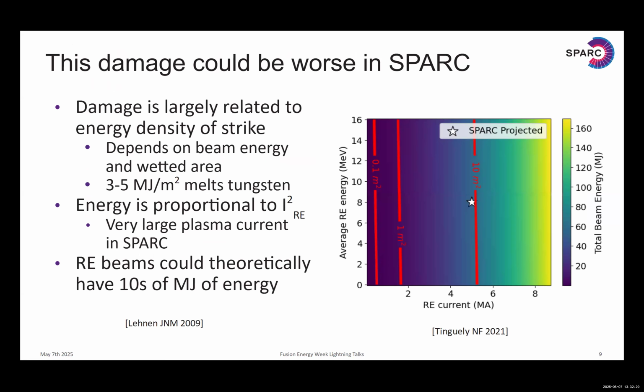So if we look at this more quantitatively, we can see that this damage could be worse in Spark because Spark has so much stored energy. The damage that a runaway electron beam can cause is largely related to both the energy of the beam. If you have a very high energy beam, you can melt a lot of material. But it also depends on how large of an area that beam strikes. If you hit a very small area, you deposit a lot of energy into that area and you're going to really melt a good section of that. However, if you spread out that energy over a wider area, maybe you won't hit a melt threshold and you'll just cause the area to heat up, but it won't quite hit melting.